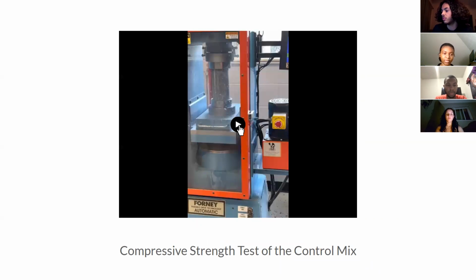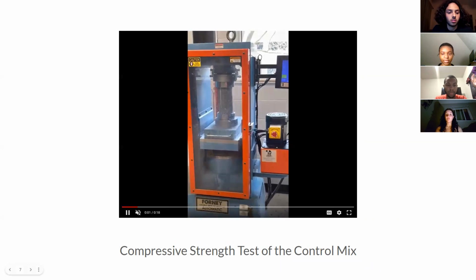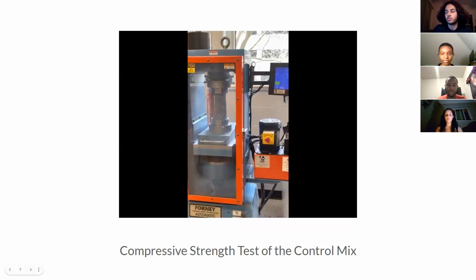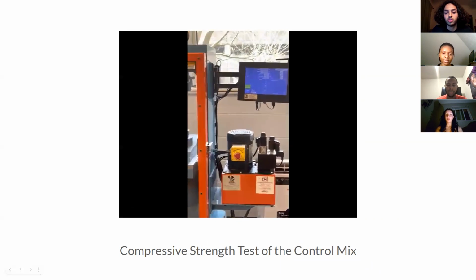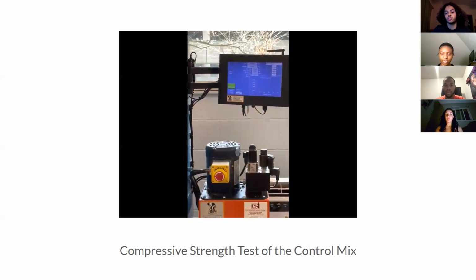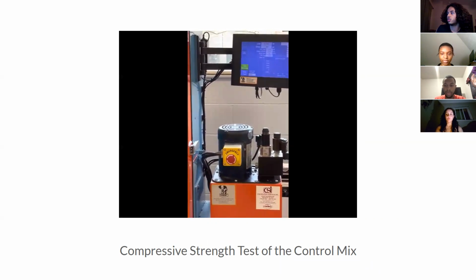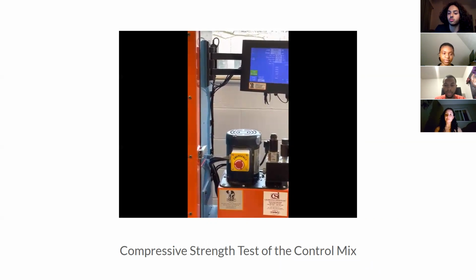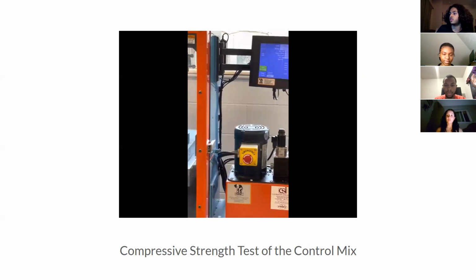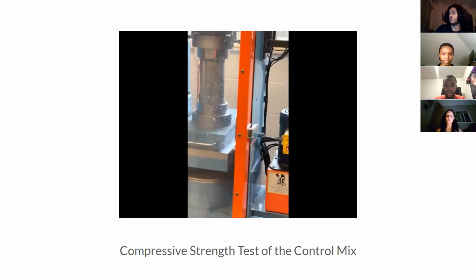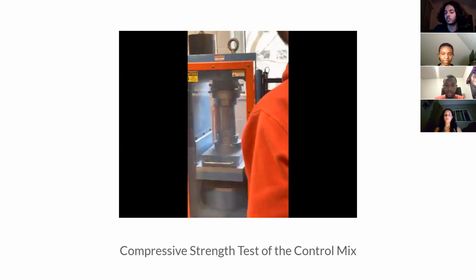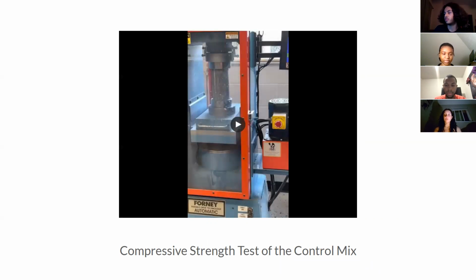And this is a video of the compressive strength tests for the control mix. In this video, the compression machine is gradually increasing the load on the cylinder until it reaches a max load right before fracture. About 2/3 of the way through this video, you'd see right about now that the cylinder starts to crack at its max load, and you can see that it's broken in multiple areas.